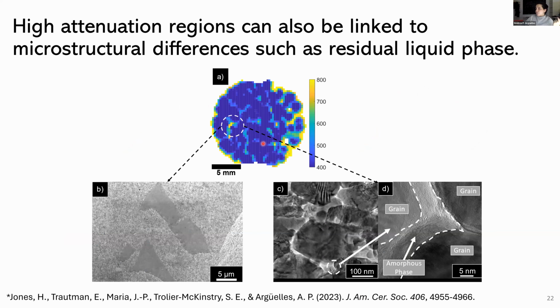And by looking a little bit closer at that, so for example, at this feature over here, we saw a couple of different things. One of them, this was really interesting to see. So the sample was pretty uniformly porous across the whole volume. And it was actually the highly densified regions that you see kind of in this area over here that were acting as scatterers, or at least that's our presumption for now, because the rest of the relatively porous area is homogeneous as far as the ultrasonic wave is concerned. And now we're dealing with a sharp change in that impedance once we get to a region that is essentially 100% dense.